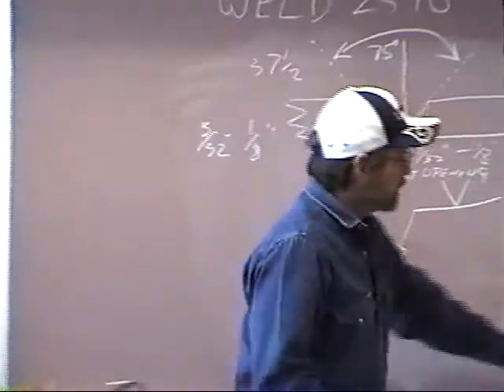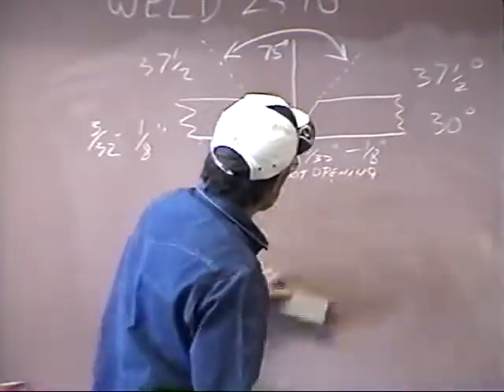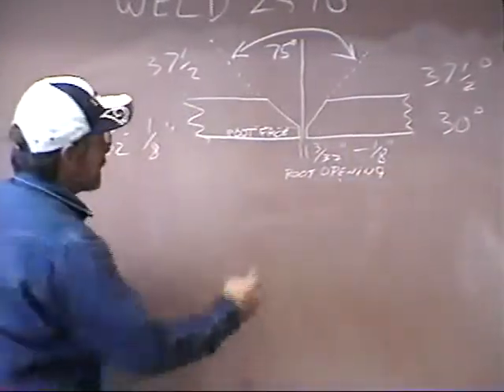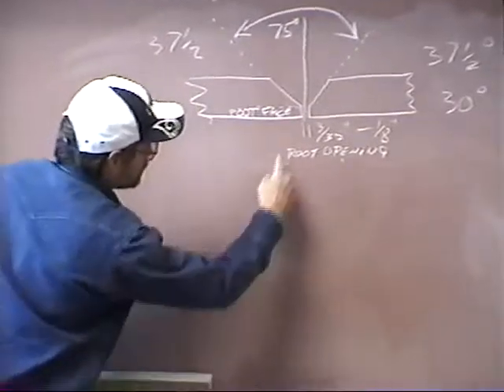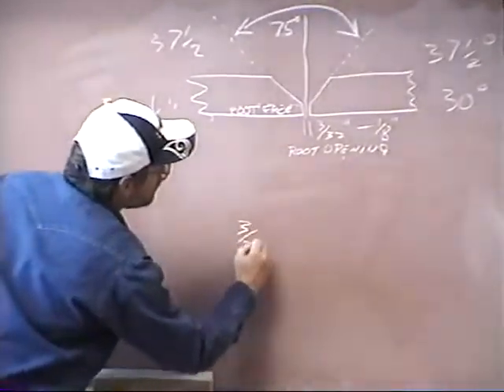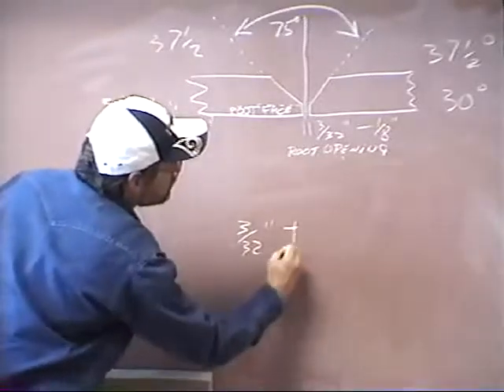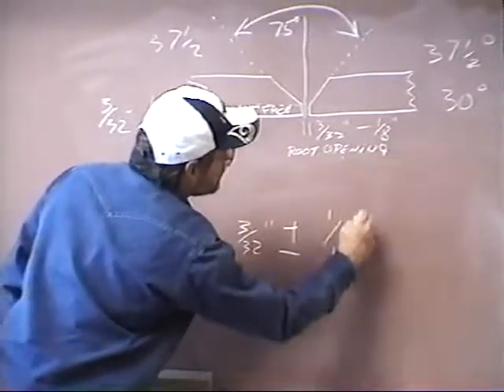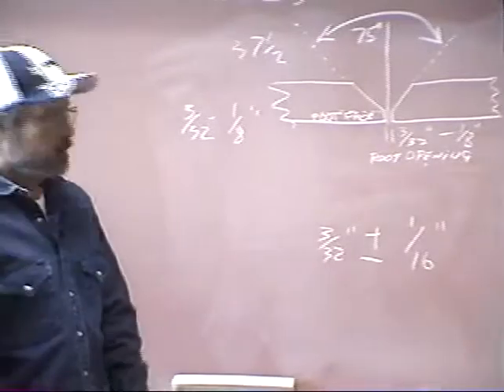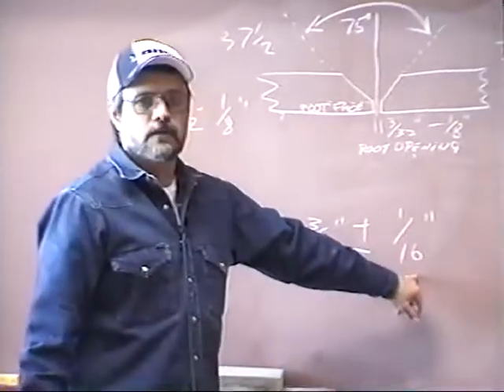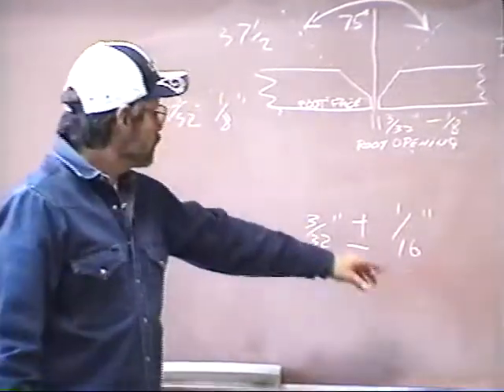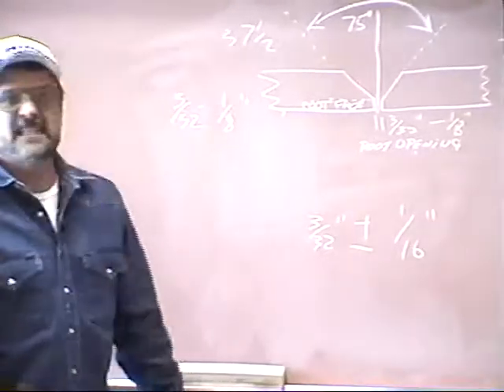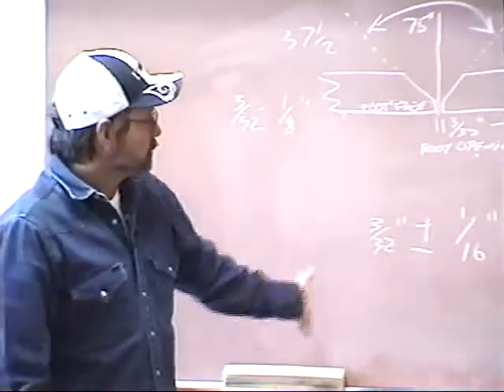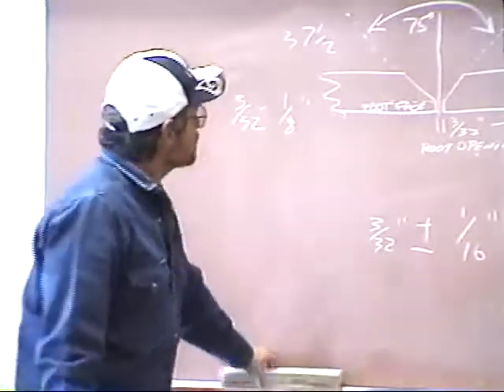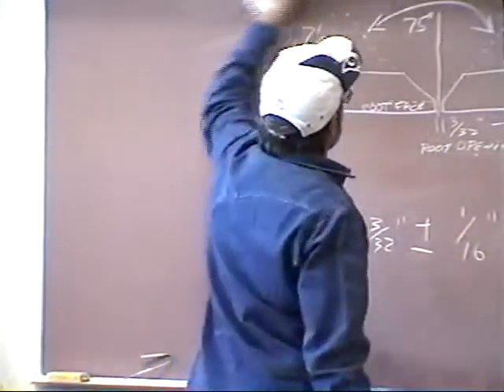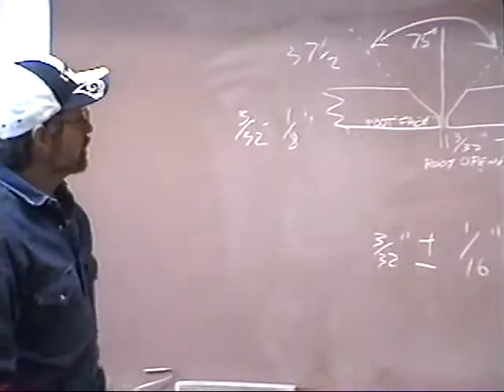Generally, your welding specification will say for your root opening, 3/32 of an inch plus or minus 1/16. And that really covers a lot of it. You can go up to 5/32 of a root opening if you want to. Or you can go down to 1/16 of a root opening if you want to. So that really gives you a lot of room to play with. But that is typically what you're going to see and what you can expect to run into.